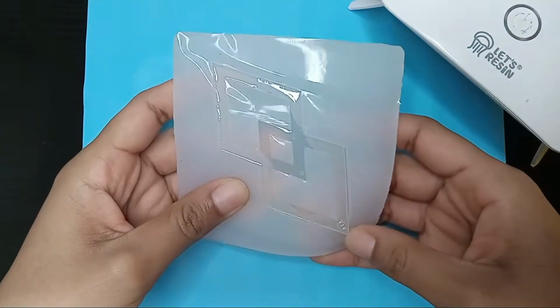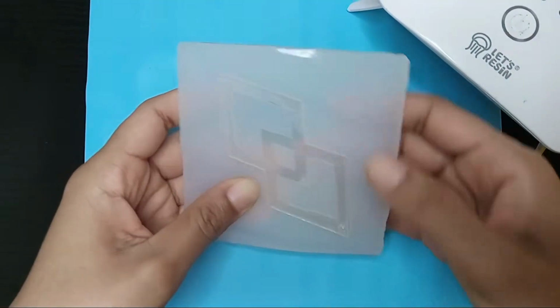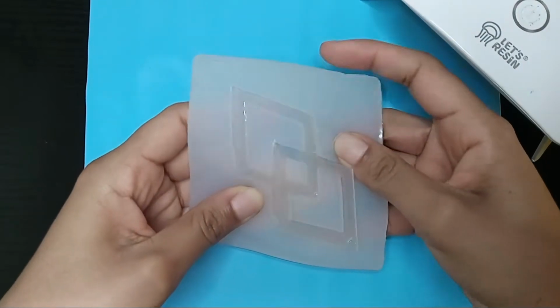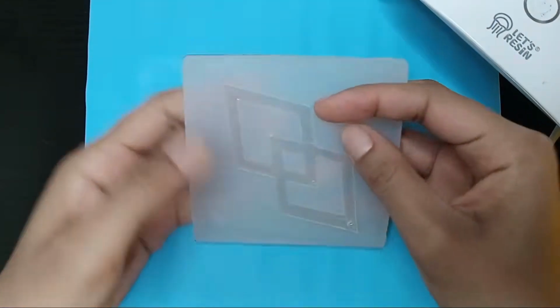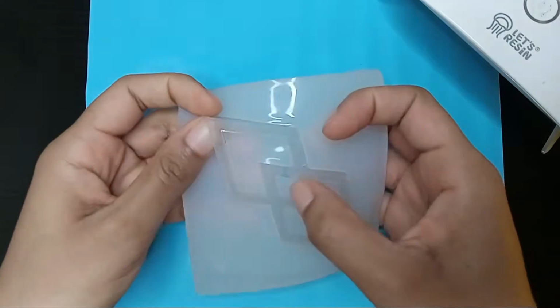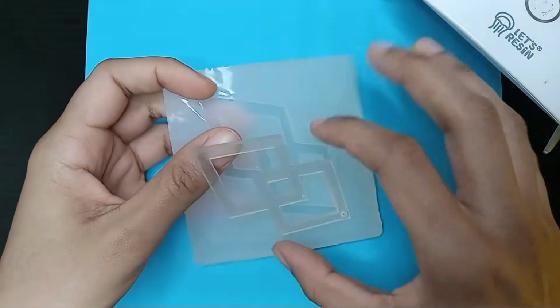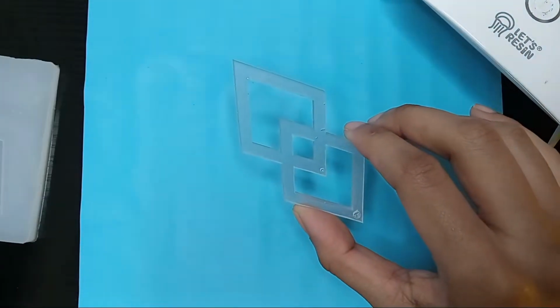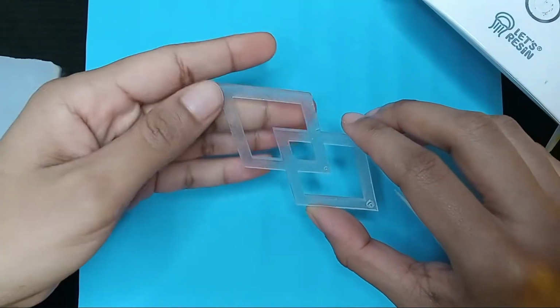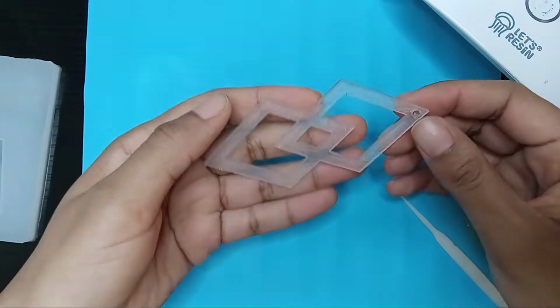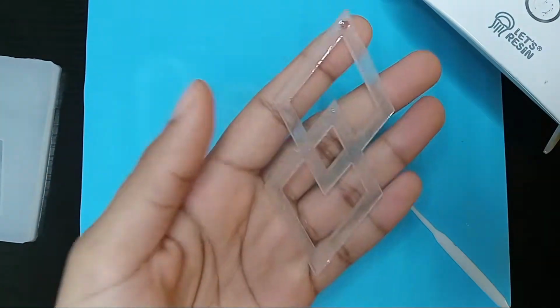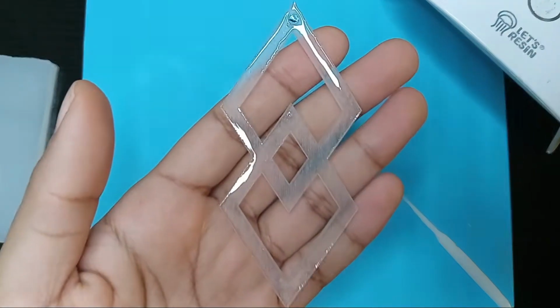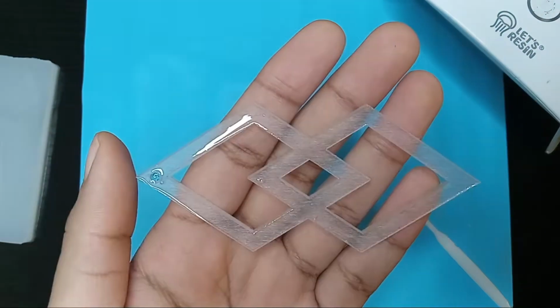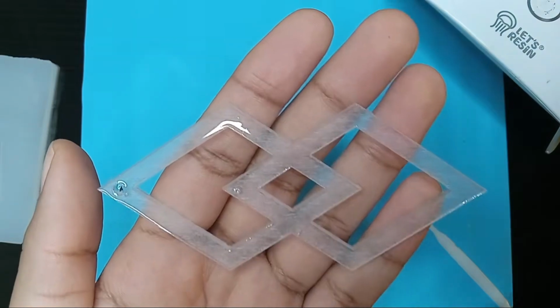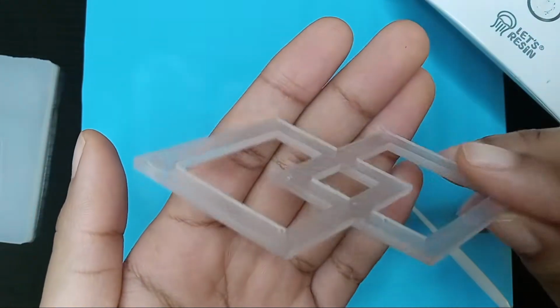It was way easier to take out the UV resin compared to taking out the epoxy resin, and I think it could be because the mold needed more time to completely cure. I added the epoxy resin to the mold one day after the mold cured, and maybe I should have waited 2 or 3 days after. But the temperature in my home is very bipolar, and I think it takes longer for the silicone and epoxy resin to cure. There were bubbles in the cured resin, but I didn't feel like getting rid of them.